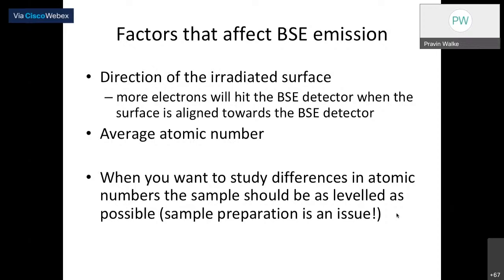When we look into dark field and bright field imaging techniques of this microscopy, SE and BSE play a very significant role. High energy and low energy are also important to give good imaging of the system. Also, we need to know the average atomic number of the system, which also affects BSE emission, right? If someone wants to study the difference in atomic numbers of the given sample, vice versa, we can also identify the atomic number of the sample. But it's quite challenging because you have to level the sample very accurately, and sample preparation would probably be the major issue if you want to measure the atomic number using SEM imaging.